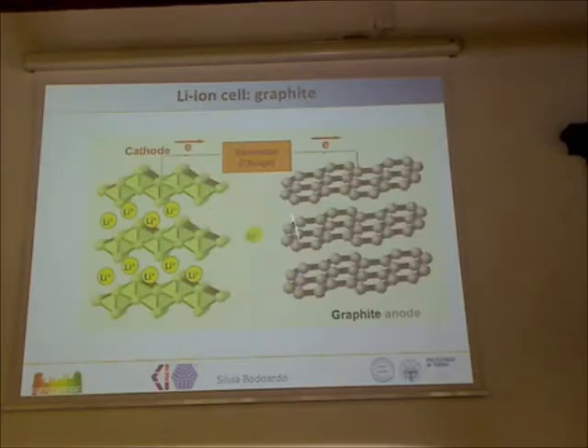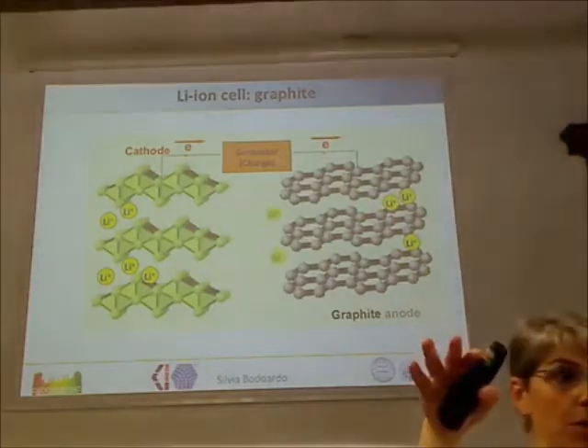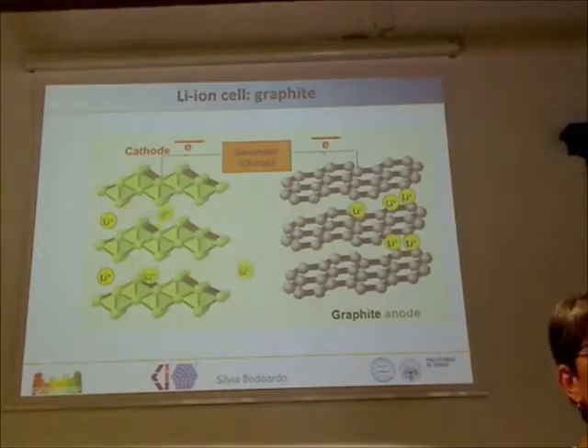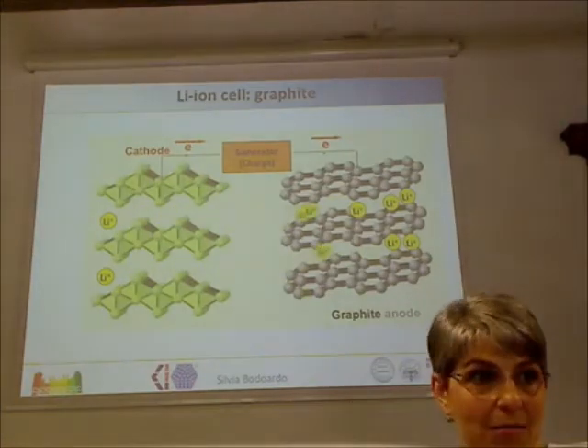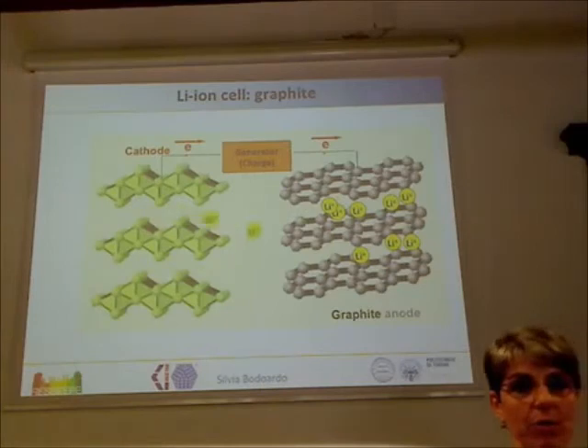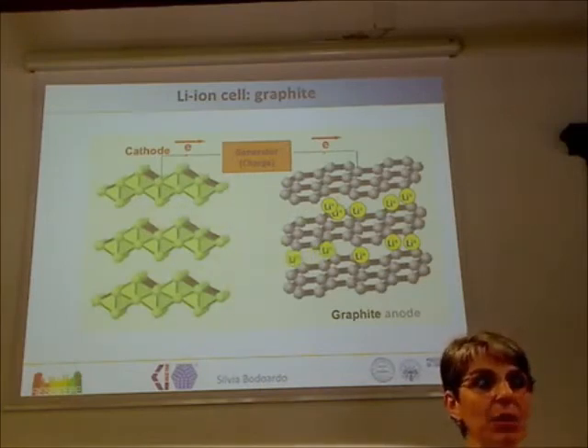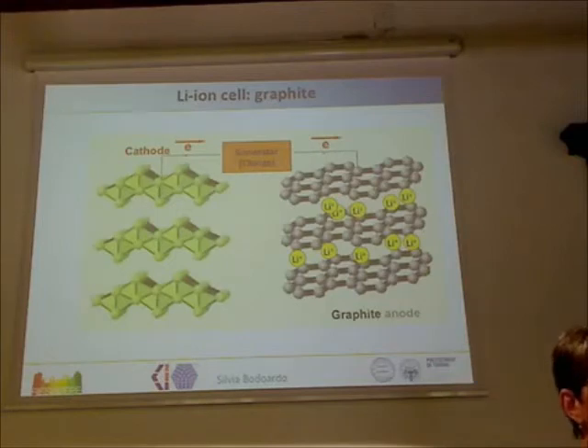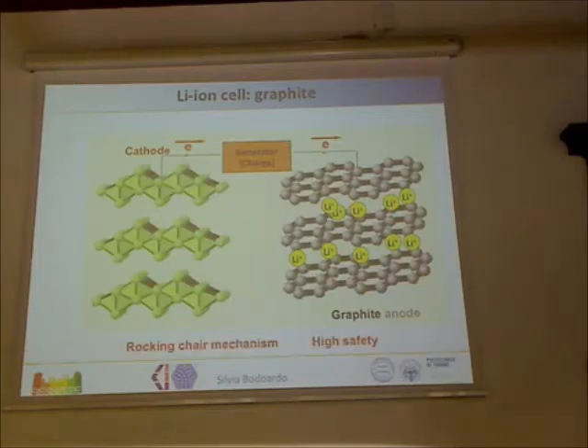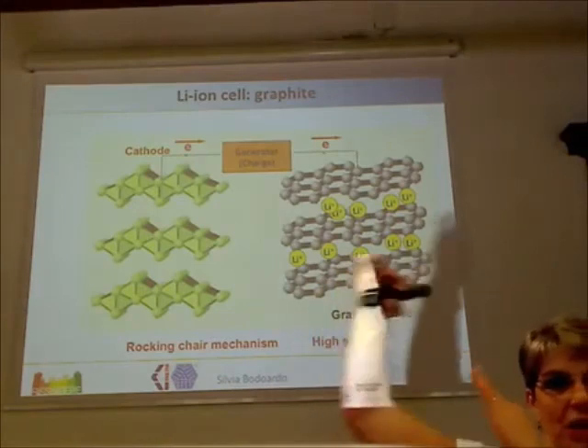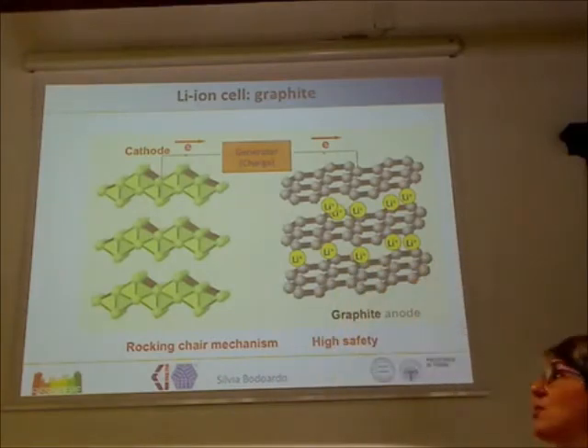So for this reason, the idea is to change the negative electrode by using graphite. Graphite also reduces, for sure, and it can host lithium ions. So in this case, you have no formation of any metal, so lithium is not reducing, it's graphite which reduces, and lithium always remains as an ion that moves in the electrolyte from one electrode to the other one. This mechanism of lithium moving from one position to the other is called the rocking chair mechanism, like a rocking chair that moves from one position to the other one.